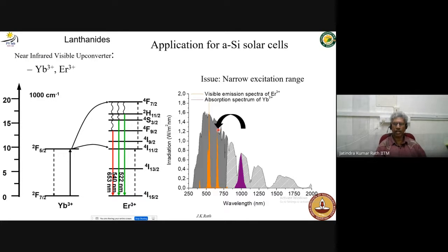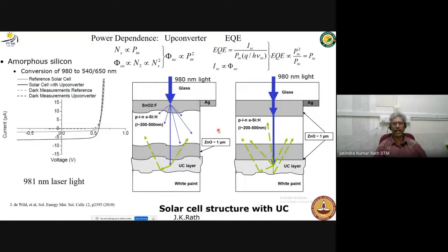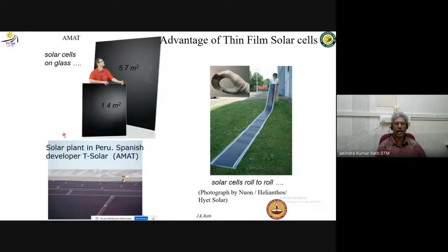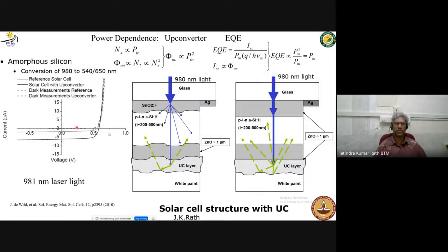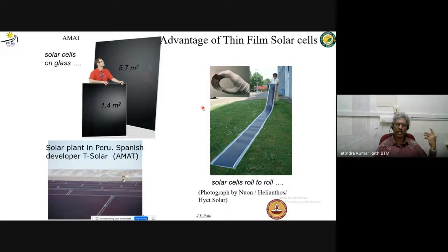So this principle is actually good, and it works pretty well in the material. However, when you make a solar cell, we tried different types of solar cells, putting up conversion on the backside of amorphous silicon. There was an increase of current, but you need really very high light, even laser light, to see the difference. You can publish a lot, but commercially it's still a long way to go. But the idea is that this sort of thing has to happen sometime, because thin film solar cells have a big future.